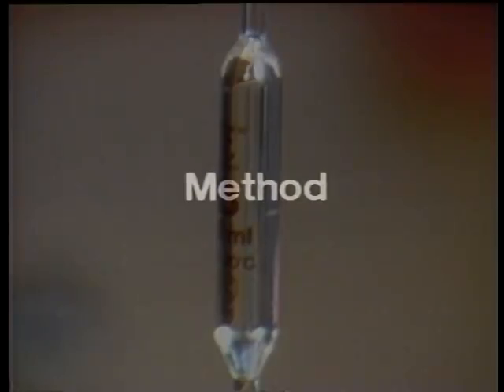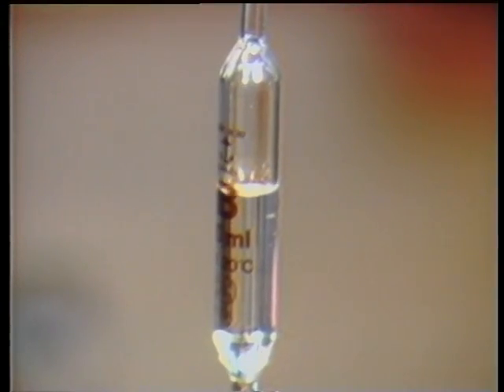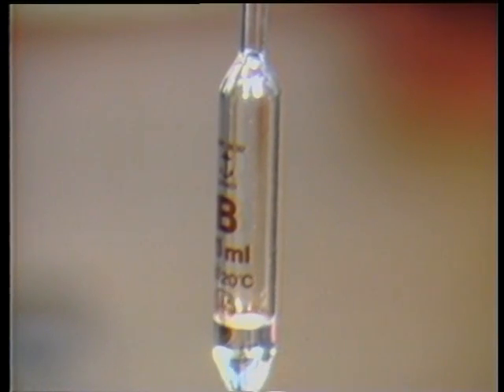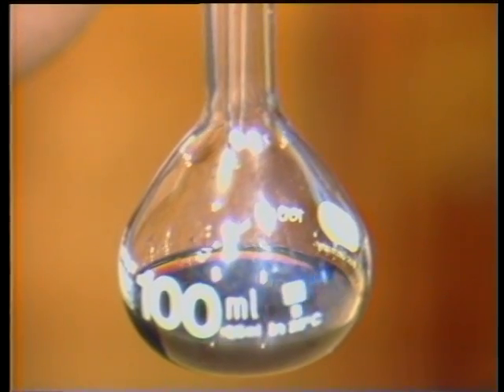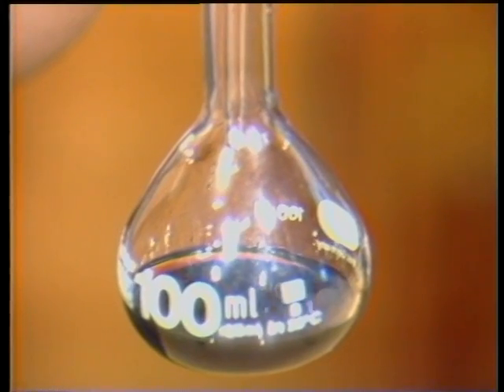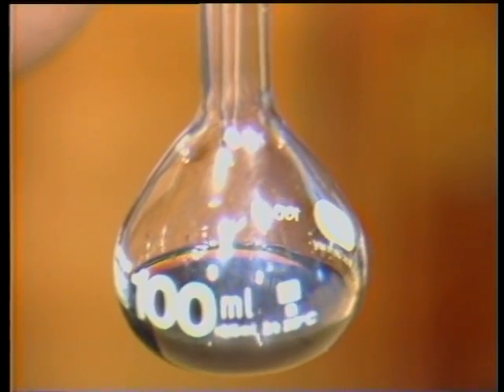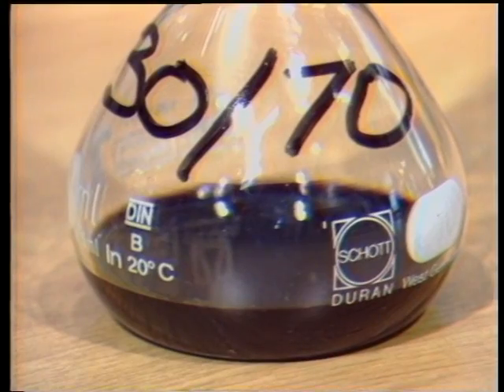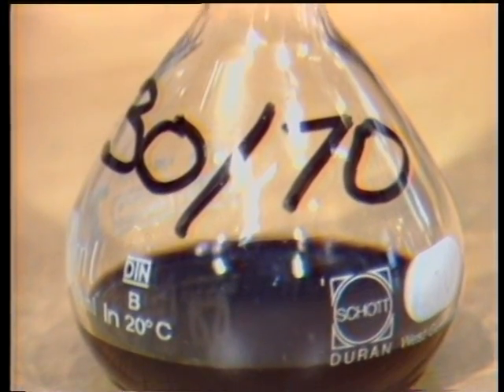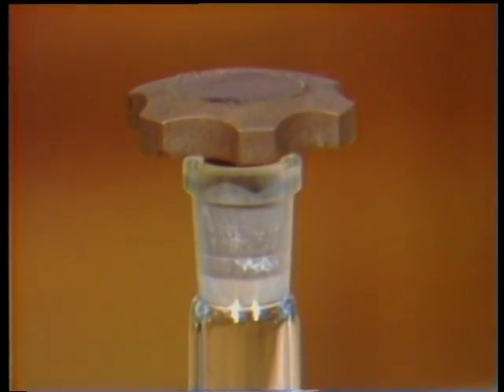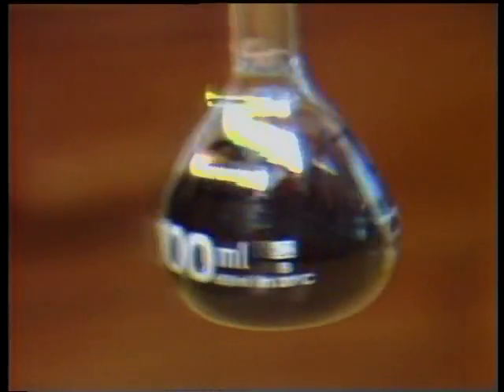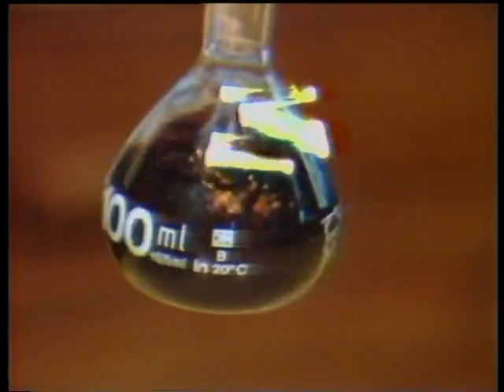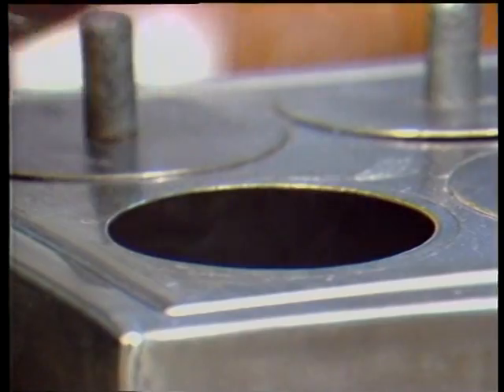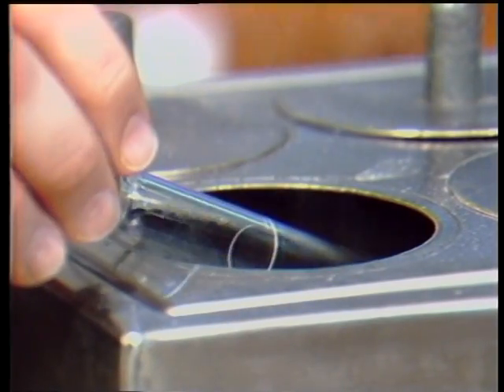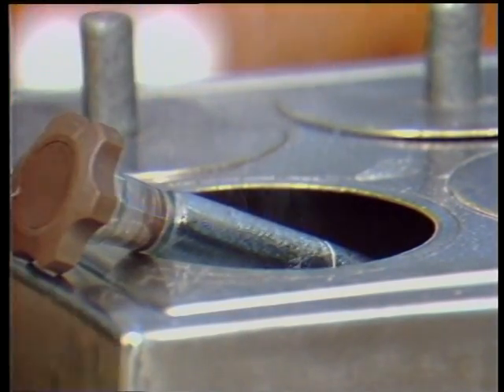Method. With a 10 milliliter pipette, add the various xylene heptane solutions to the flasks. Rinse the pipette out with the solution before transferring it into the flask. Label each flask clearly. Insert the stoppers. Shake and rotate the flasks for 5 seconds. Place the flasks in a boiling water bath for 1 minute.